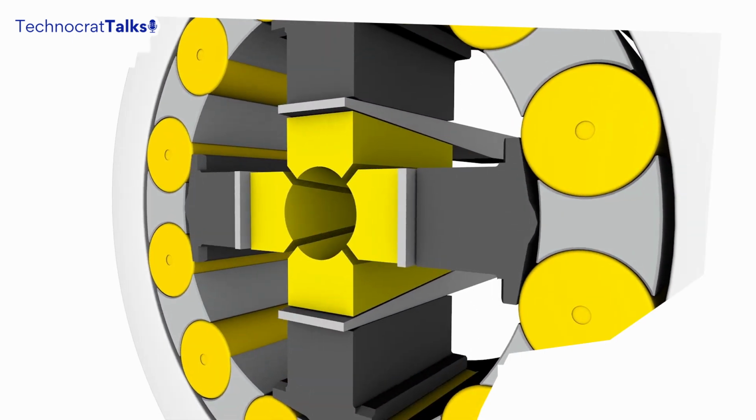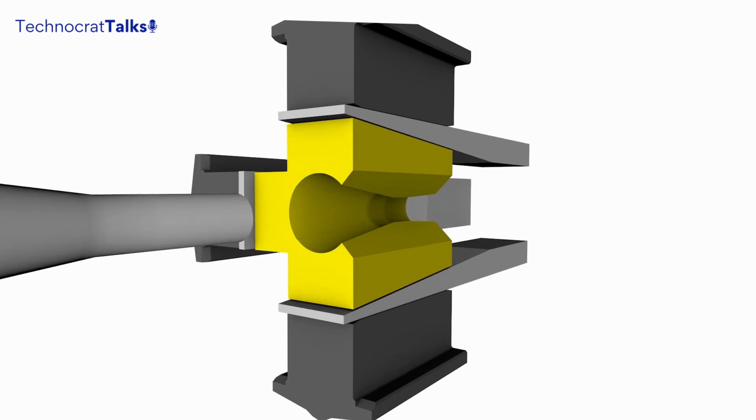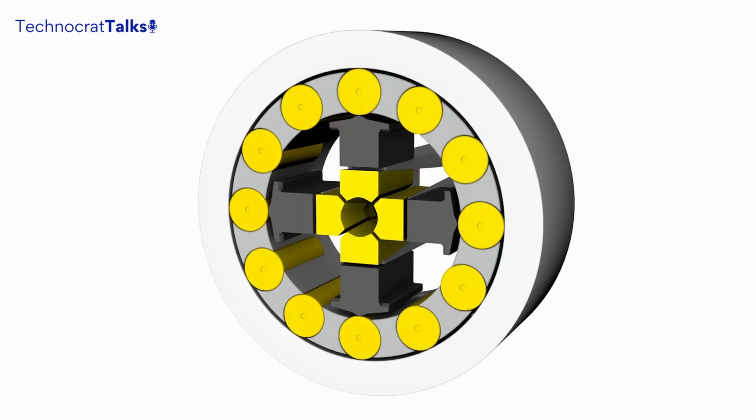First, they did this rotary swaging technology. Rotary swaging is something like a sledgehammer: two hammers working against each other, with material in the middle, and you start forming this material. From this very basic idea, we started with in-feed swaging. Then they developed the recess swaging technology and added some CNC programming to it. Today we have machines which do a rotary swaging procedure completely CNC controlled, so you can move the material from one portion of the part to another wherever you want. So this was forming in the radial direction.